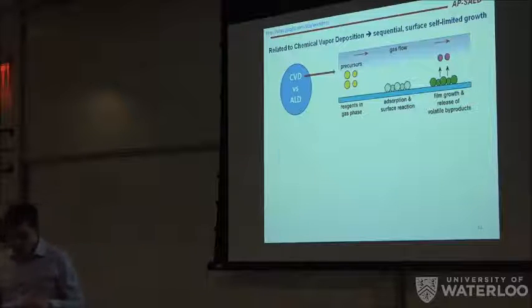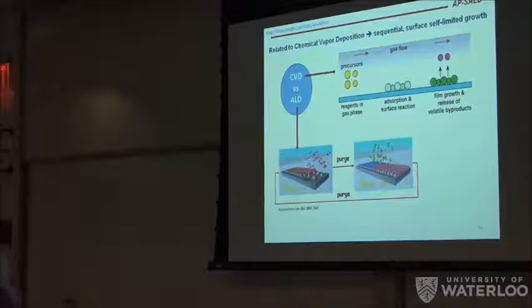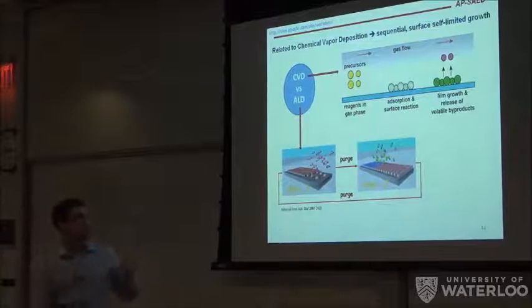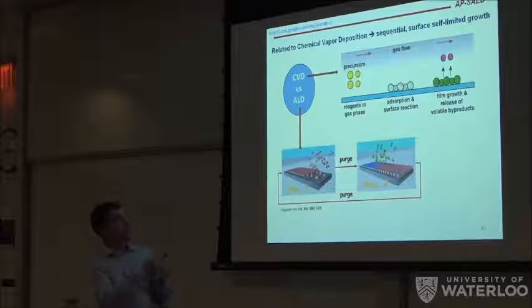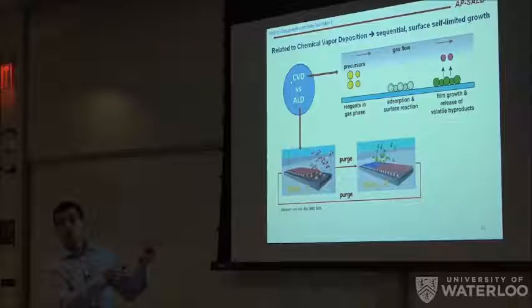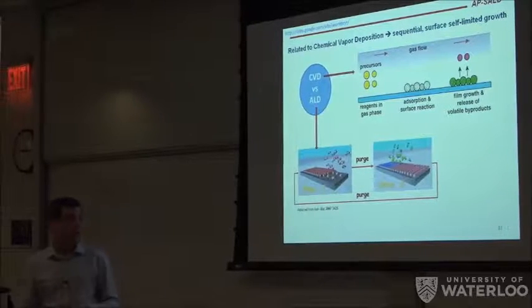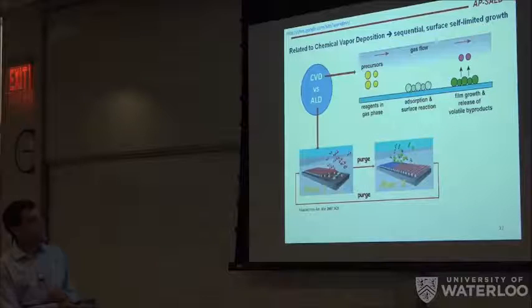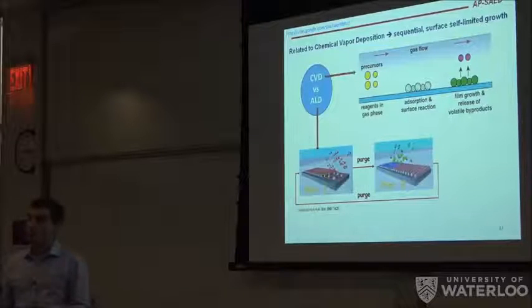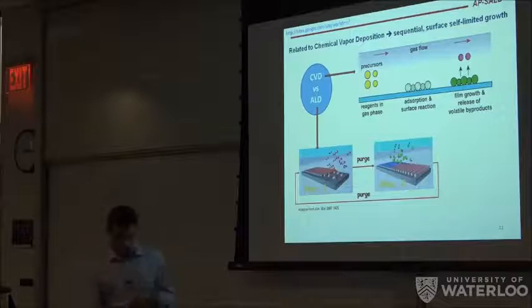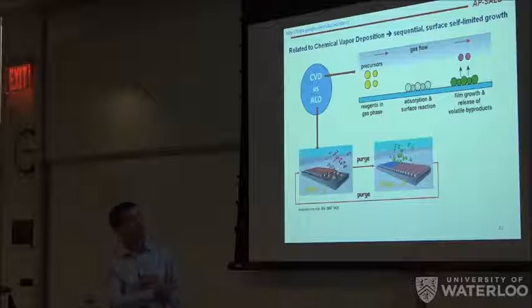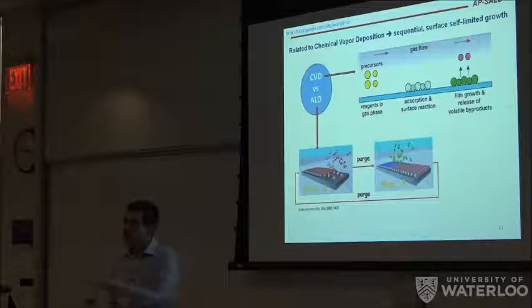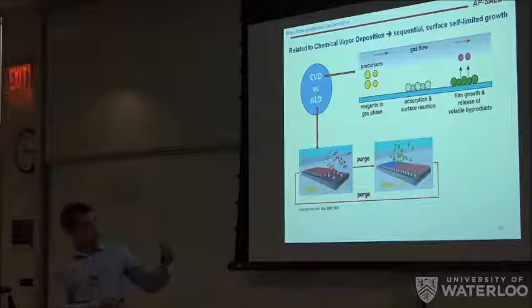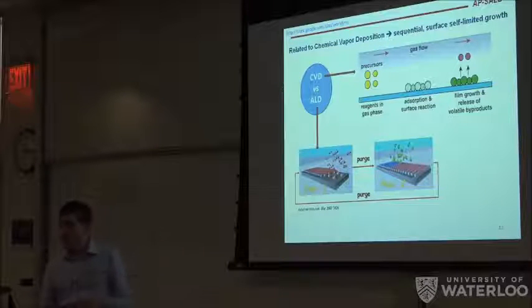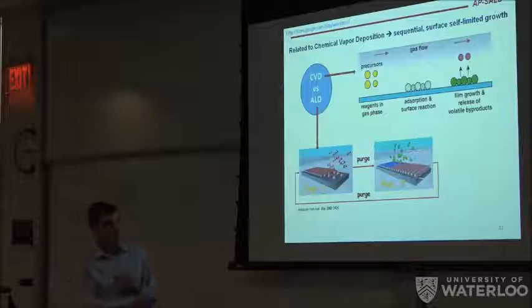But you can do that, but you can also do a sequential exposure of your substrate to the precursors, and that's what transforms CVD into atomic layer deposition. It's basically very similar, but in this case, you first expose your substrate to the first precursor, and you give it enough time to saturate the surface. When all the surface has reacted, you have your monolayer formed. The excess precursor is purged, and then only when everything is clean, you inject the second precursor that can only react with the first monolayer.